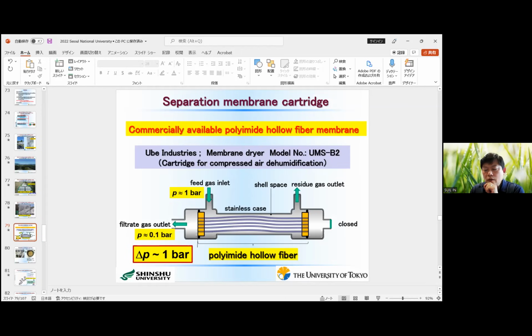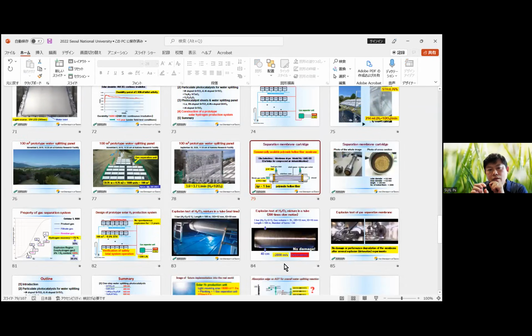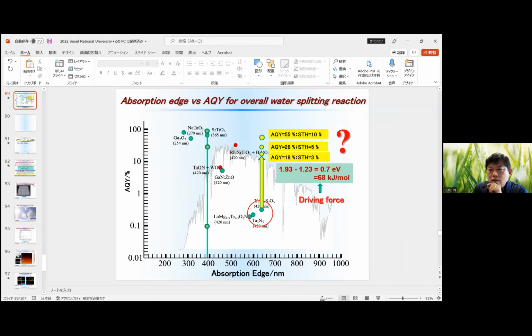I see. The second question is, at the end of your talk, you said 0.7 electron volt for the driving force to achieve AQY 55%. What does that 0.7 electron volt driving force mean? Do you mean to make a photoelectrochemical electrode? No. As I show here, if we use this yttrium titanium oxysulfide, the band gap energy is 1.93 volt. To thermodynamically split water into hydrogen and oxygen, we need 1.23 V. So the remaining energy is 0.7 eV, which is 68 kilojoules per mole. This is excess energy we can utilize.